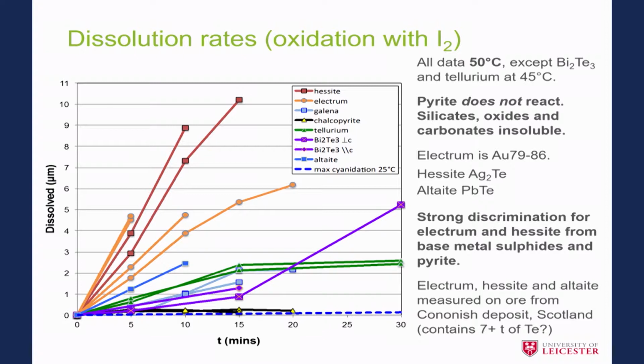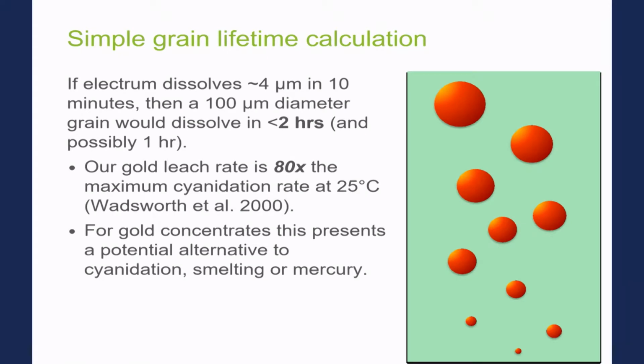Okay, now if we just look at the rates and look at the quantification of them, if we just look at this point here, so the lowest rate measured for the electrum, and there is quite a variation here, so I can explain that later on perhaps in questions. But if we take that point, 10 minutes, we've dissolved 4 microns. Okay, let's just do some very simple calculations. If it dissolves 4 microns in 10 minutes, then even if we have a big grain, 100 microns diameter, then that would dissolve in less than 2 hours. Okay, and if we use the fastest rate, 1 hour.